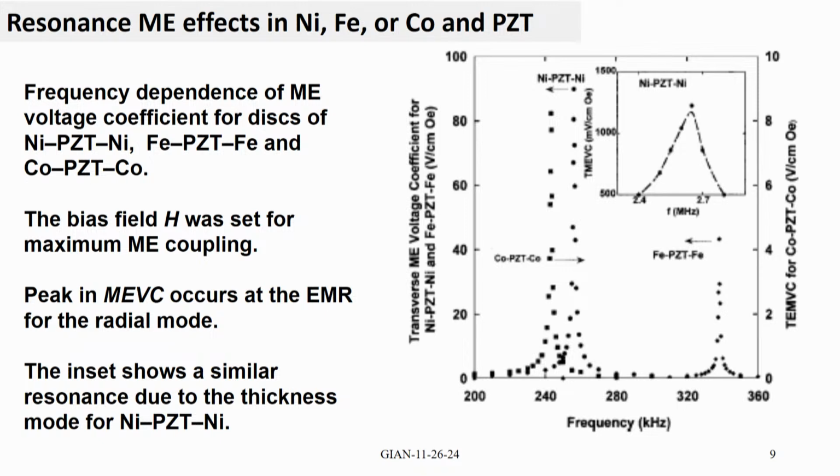and so on. But cobalt is also not very high. It is on the order of 10. Yeah, it's about 9 volts per centimeter per oersted. Iron is much higher than cobalt. It's about 45. So among the 3D transition metals, nickel has the highest value.